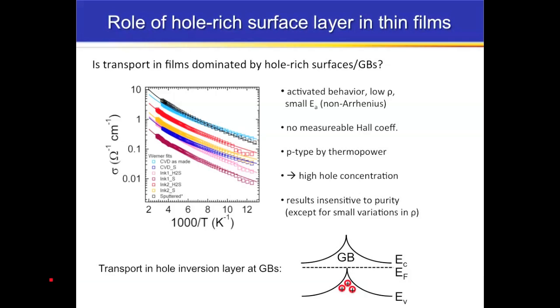So if we have this inversion layer present in pyrite, this could very easily explain this kind of behavior, that we have all P-type characteristics and its high hole concentration. That's because if you consider what's happening at a grain boundary, if you have this sharp band bending at the surface, at the grain boundary, you're going to have the propensity for holes to sit basically at that surface site, at that interfacial area there. And you could have hole conductivity along grain boundaries basically dominating your properties no matter what temperature you're at, okay? Because you just have so much more surface than you have bulk in the case of these polycrystalline films. And we think that this is probably quite likely what's happening.